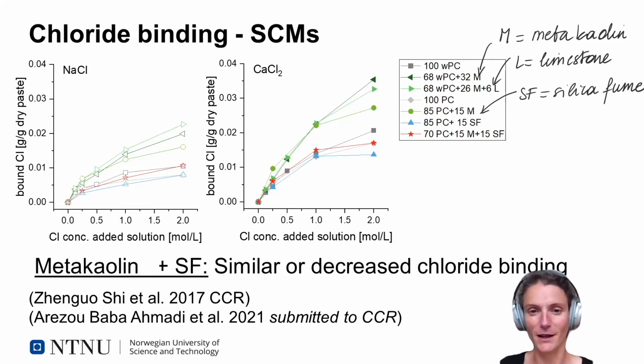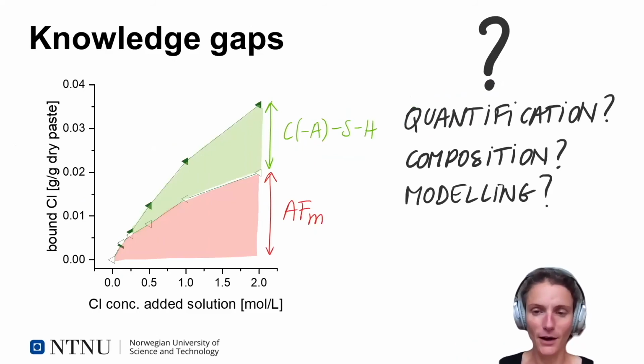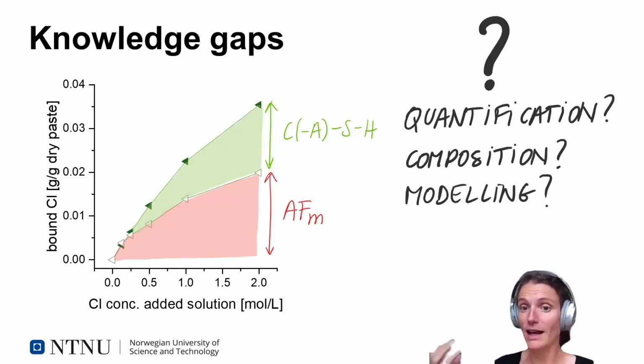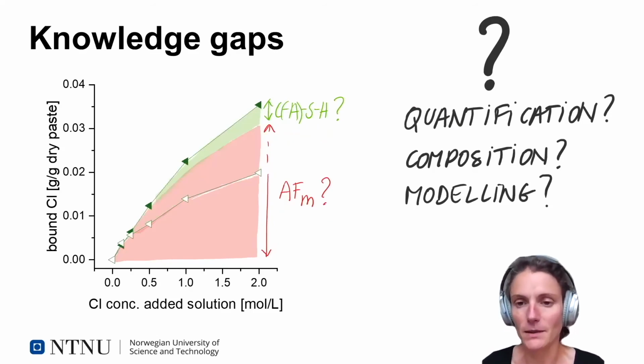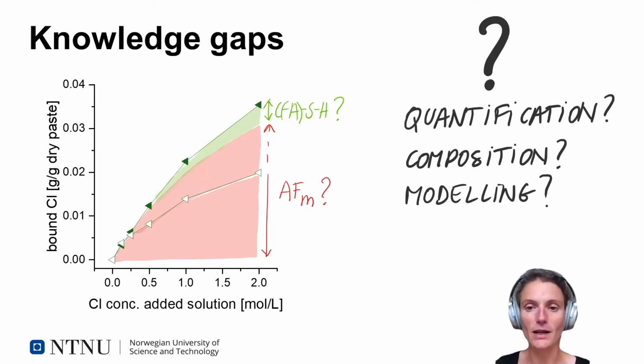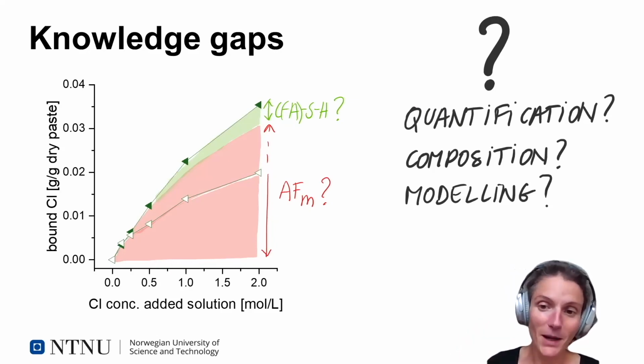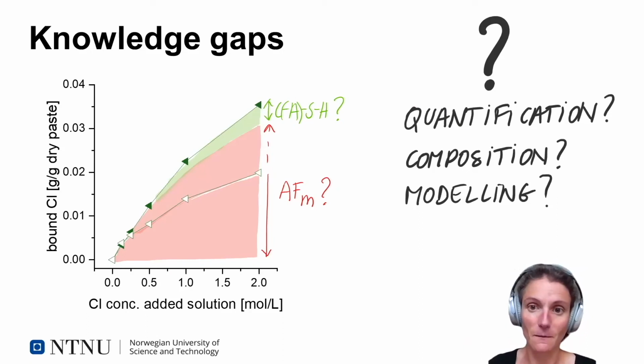control on your phases. So I'm not going to go in full depth of these 2 studies, but in both studies, we encountered challenges as we didn't fully, similar in the previous studies with the Portland cement, we didn't fully quantify the amount of AFM, check the composition, and the same with the CSH. We didn't fully quantify the CSH and determine the composition. So if we want to say something about how an SCM is affecting chloride binding, we actually really have to determine the amount of the phases formed and their compositions. And preferably, this would be in such a generic form that we can make models out of this.